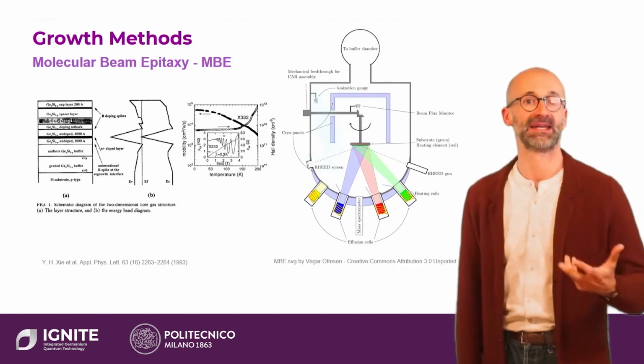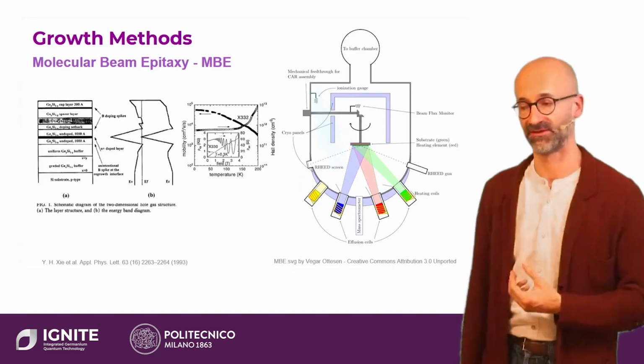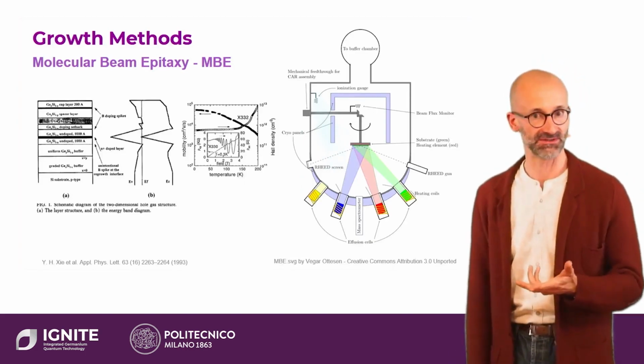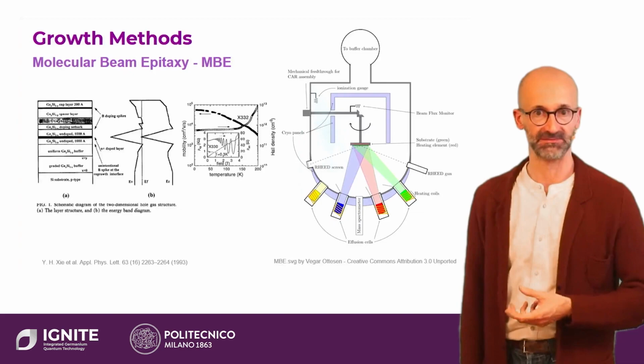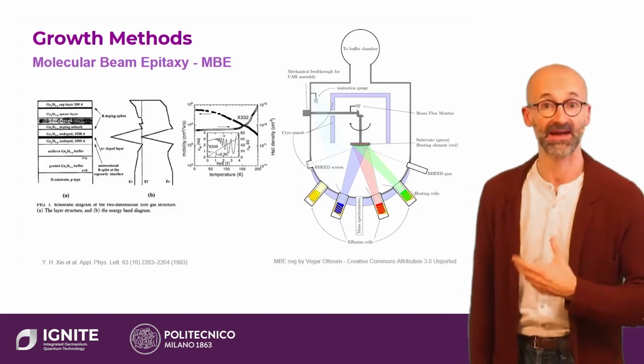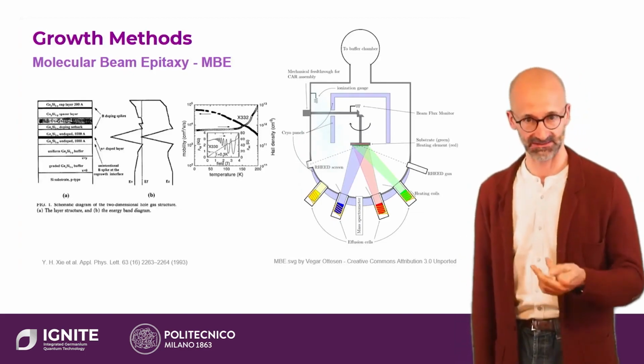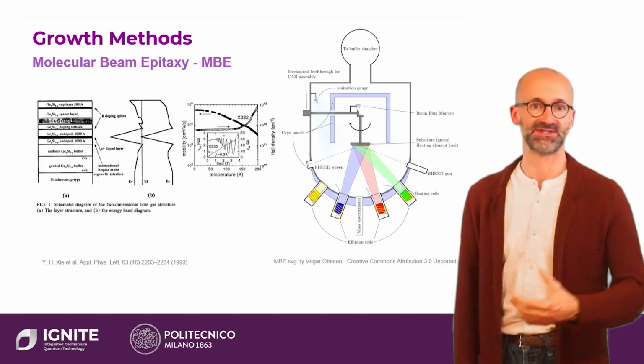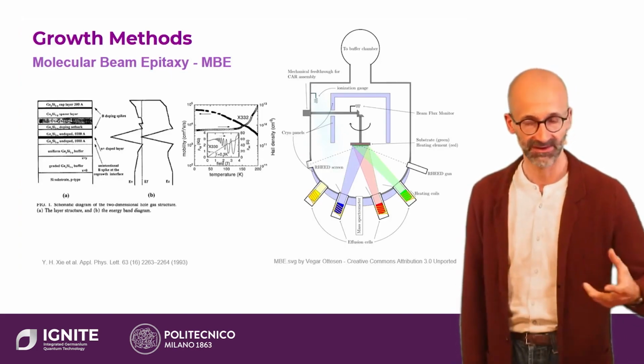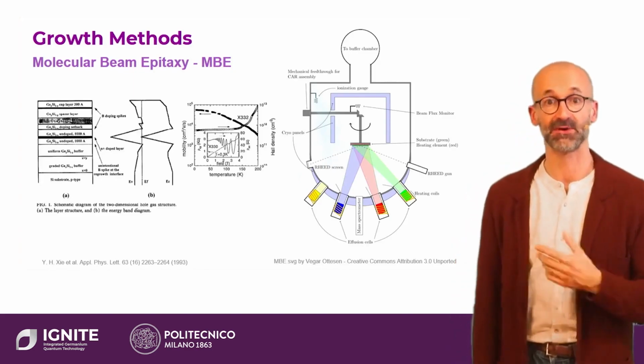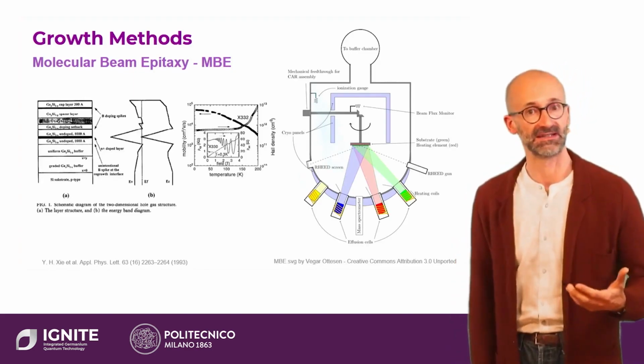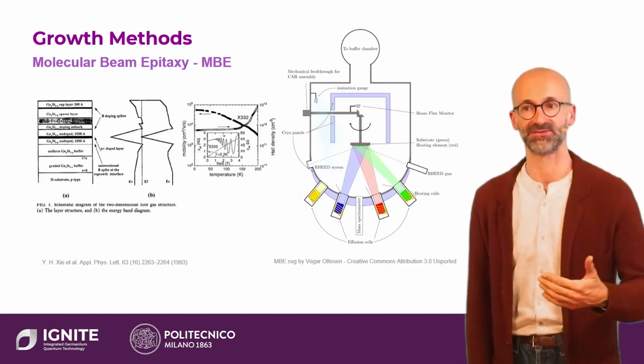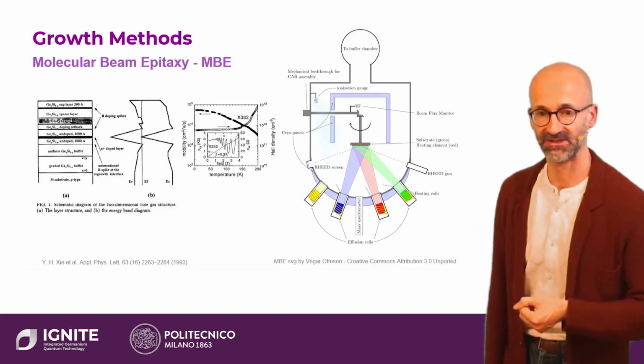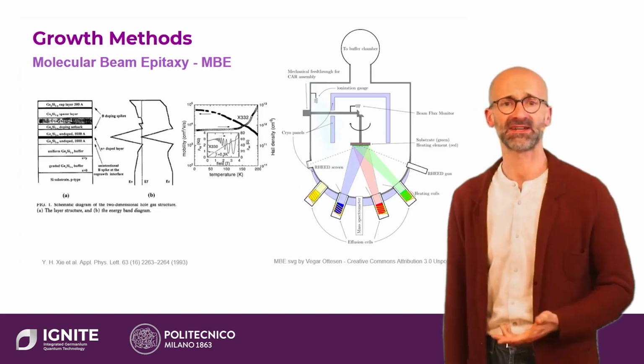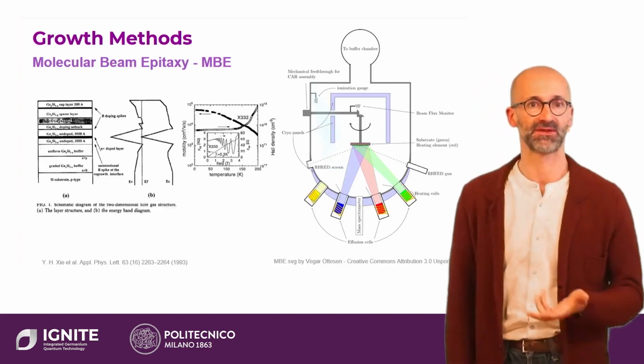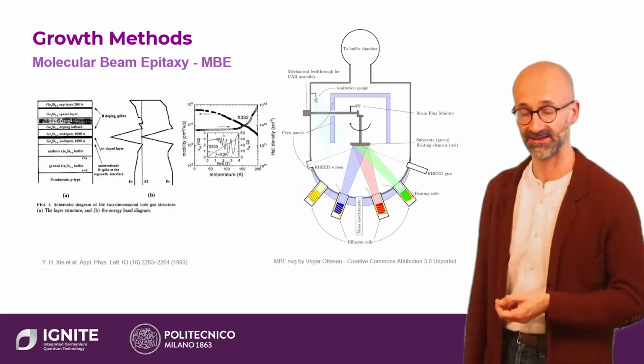And the drawback here is that to grow these thick graded buffers, a lot of these solid sources are completely consumed, and then the only way to refill them is to completely break the vacuum. And the vacuum needs to be very good for molecular beam epitaxy because we need the atoms from the sources to arrive directly on the substrate without being deflected by atoms of gas in the chamber, and we also don't need any impurities in the chamber to arrive on the substrate faster than these atoms of the material we're trying to grow. So a very good vacuum is critical in MBE, which is no good if you have to keep breaking a vacuum to put new material inside.